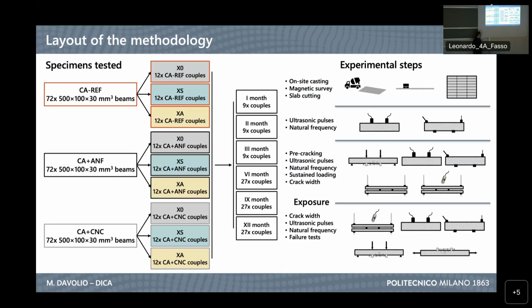So this is what we tested, and what we did is summarizing these experimental steps, which started on the side of the geothermal plant you saw in some pictures, with the casting of the slabs, which was also helpful to actually see the real condition of casting we face for precast structures on site. And for these slabs, a magnetic survey was performed, and then they were cut into the thin beams we used for our laboratory testing, which started from this first stage, where the specimens are uncracked, are safe as they were